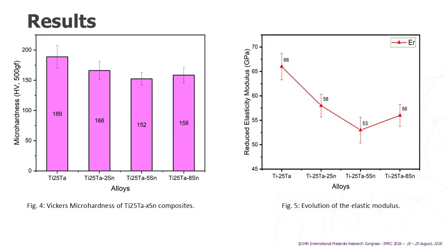In the microhardness test, lower values were obtained for the alloys containing tin compared to the titanium 25 tantalum alloy. The lowest value was obtained for the alloy with 5% tin because this composition results in greater stabilization of the titanium beta phase, as discussed earlier in the section on the X-ray diffraction test.